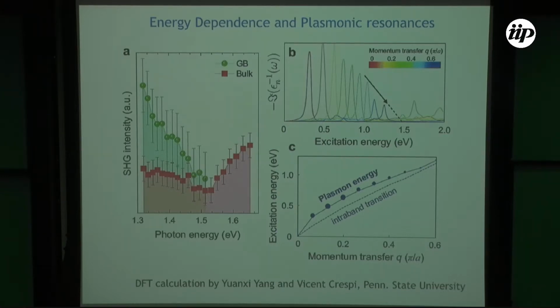Our collaborators from Penn State, from Vincent Crespi's group, the postdoc Yuanxi Yang, did these calculations. He calculated the electron loss spectroscopy, considering that the states along the grain boundaries are metallic. So he's considering the plasmon resonance of these metallic states. What he finds is that for energies below 1.5 eV, you start to have some plasmon states, and the intensity increases with smaller energy. These are the plasmon peaks for different momentum transfer between the light and the grain boundary.